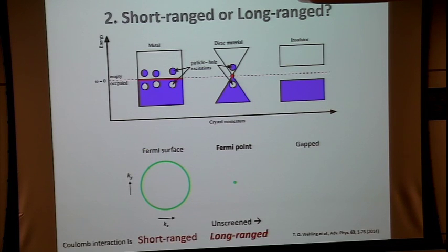And an interesting point in massless Dirac fermions is the effect of the Coulomb interactions. In conventional metals with a Fermi surface, there are many electrons, so the Coulomb interaction is screened. And short-range Coulomb interactions give a mass renormalization, where the Fermi velocity is suppressed and the density of states is enhanced. However, in the Dirac fermion states, the electron density is very small or vanishing at low temperatures. So the long-range Coulomb interaction is unscreened. So the long-range Coulomb interaction plays a vital role in the massless Dirac fermion phase.